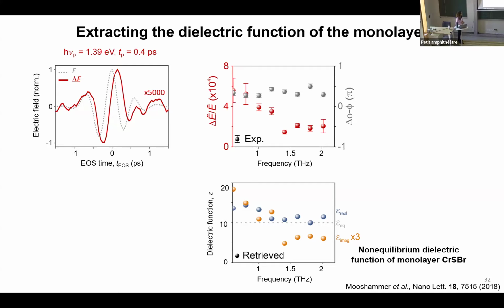So by running the algorithm, starting from an initial guess, that is the equilibrium dielectric function of the monolayer that I show with the dashed gray line here, we could retrieve the real part and the imaginary part of the dielectric function. And what we saw is that both of them show an increase on the lower frequency side of the spectrum. This is very much like a Lorentz oscillator-like behavior. So it seems that we are having some transition between bound excitonic states.